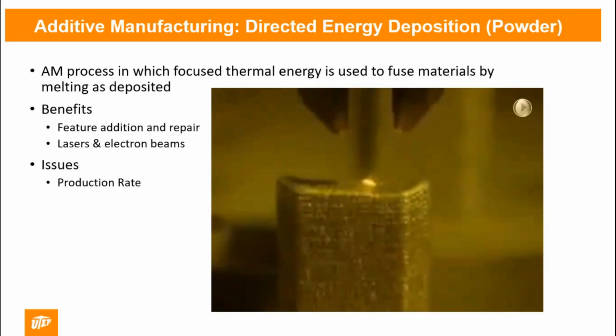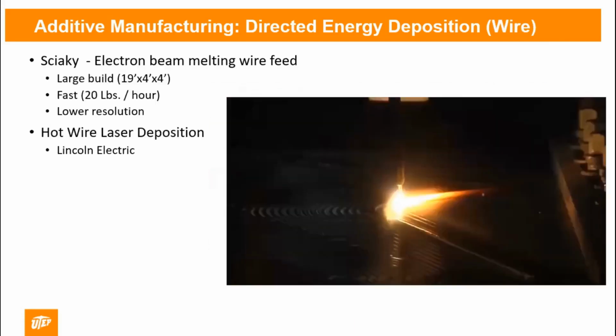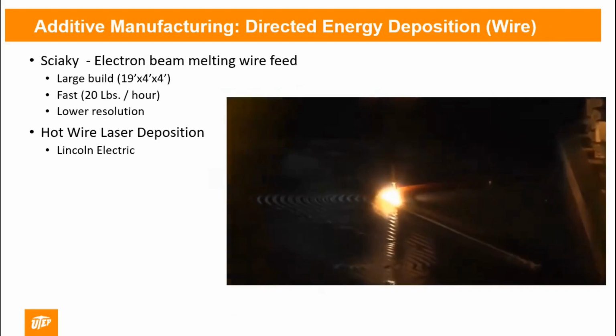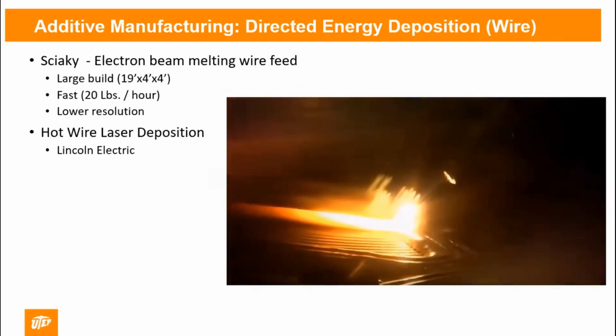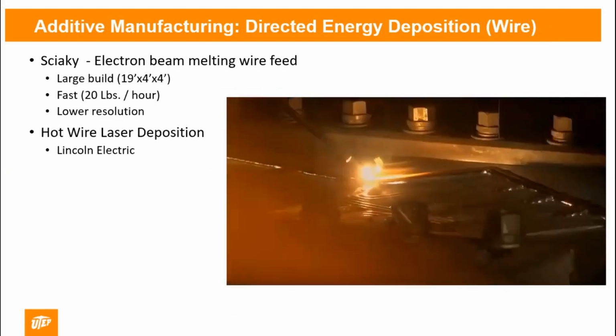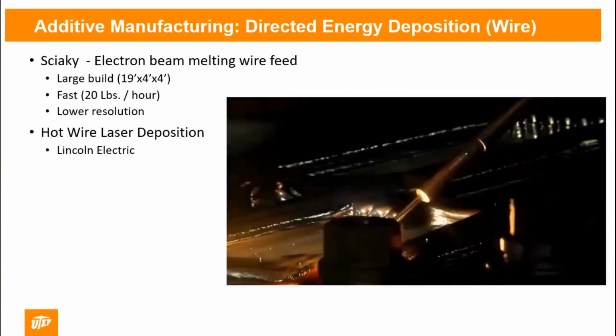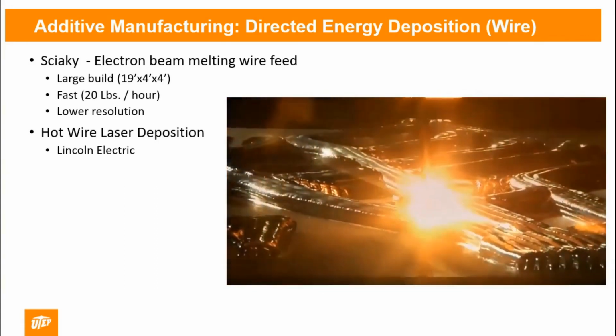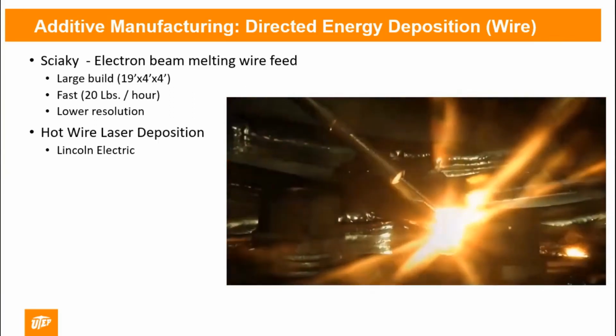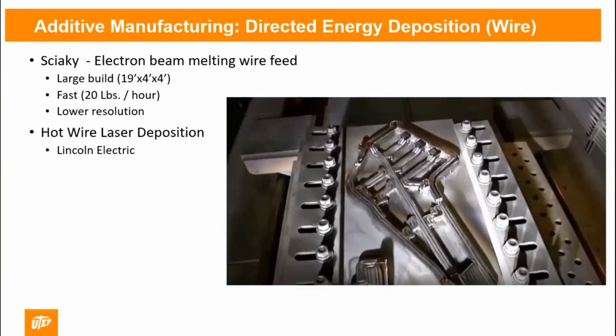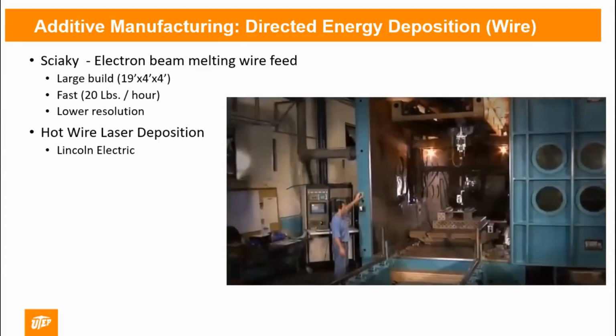It doesn't have the resolution that you get from powder bed fusion, but generally speaking, the deposition rates are much higher. So you can build bigger parts faster. And actually the powder version of it's not that great for production rate when you compare it to this system, which is in an evacuated chamber with a wire and an electron beam melting the metal. And from a production rate standpoint, this is by far the fastest metal 3D printing process.